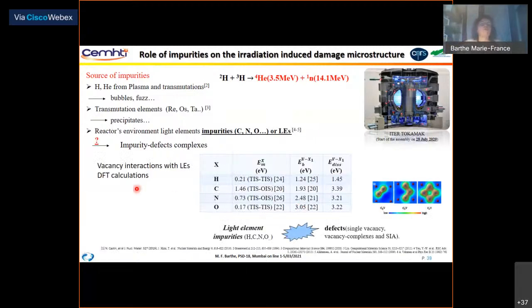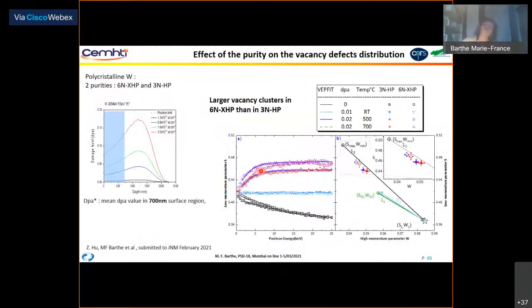Concerning the vacancy, there is also some interaction which is expected from DFT calculations. The binding energy between these different types of light elements and the vacancy is higher than 1.2 eV, and can reach 3 eV for oxygen, for example. It is also possible to trap several of these atoms in the same single vacancy, for example here for carbon in a single vacancy. Then we decided to study what will be the effect of the purity on vacancy defect distribution.